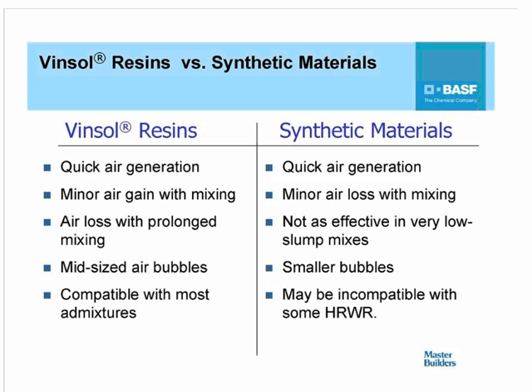Now, these vinsol resins and rosins tend to form mid-sized air bubbles, and most of them are basically formulated and are compatible with most chemical admixtures that are used in concrete. Now, the synthetic materials also generate air quickly, but they're not as effective in very low slump mixes, such as those that may be used in paving applications.